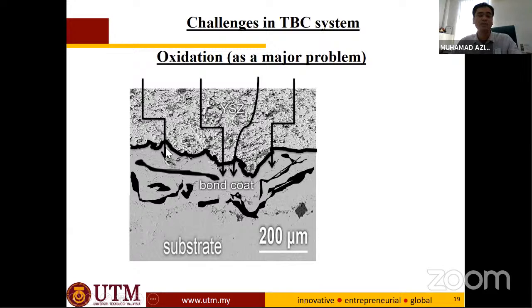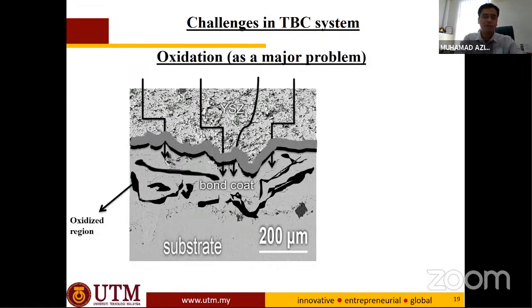So we need to control the growth. How do we control the growth? We create another layer here, which is an alumina layer or other ceramic layer. Of course, it's ceramic. Okay, right. This is basically another problem in the ceramic coating. So you will see this oxide next to the alumina.